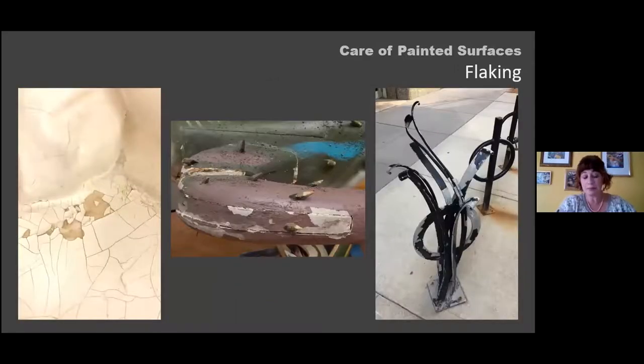Flaking and peeling arise from poor adhesion or cohesion — there can be failure either within the paint layer or at the interface. You physically lose large chunks of paint. Examples include paint on plaster, paint on wood, and paint on galvanized steel in an outdoor environment. This can result from physical force, vandalism, fire, water, pests, balloons, light, and temperature — again, all agents come into effect.